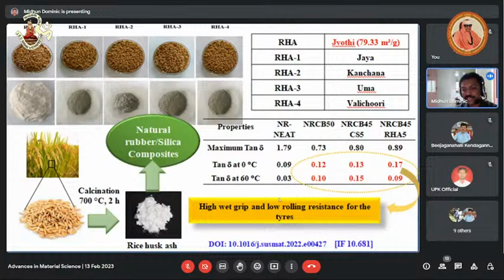Another parameter that is under our investigation is tan delta at 0 degrees Celsius. That is a parameter that determines wet grip, so that when the passenger vehicle runs over the road, it does not skid. The higher the value of tan delta at 0 degrees Celsius, the higher will be the wet grip, and the lower the value of tan delta at 60 degrees Celsius, the lower will be the rolling resistance.